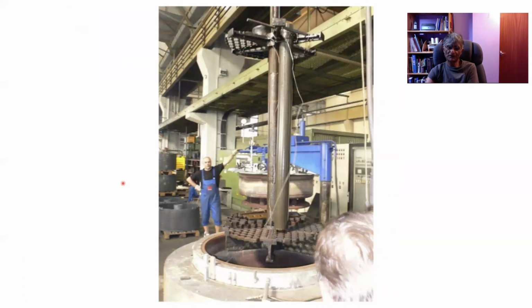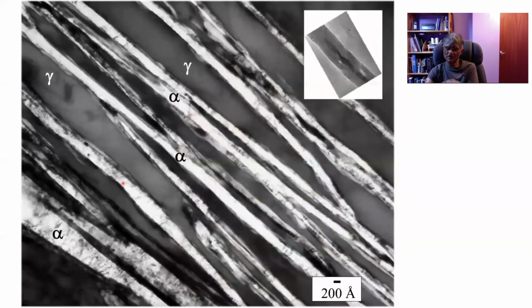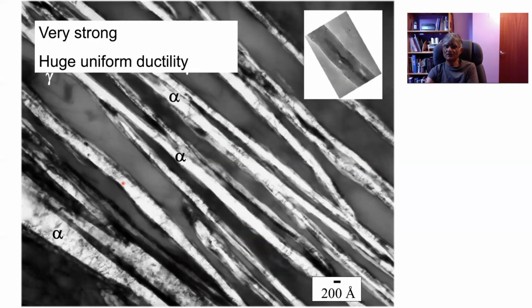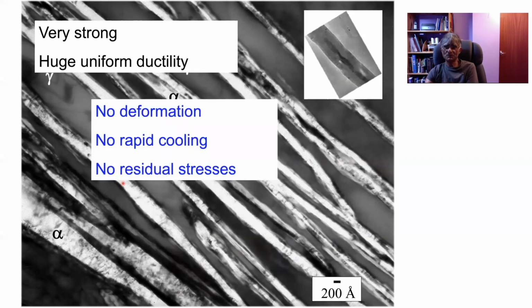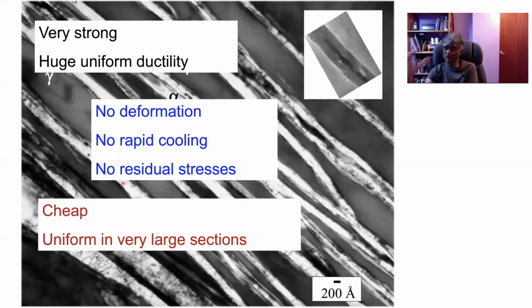Okay, so here are two of these shafts heat treated, and they have this structure throughout, uniform hardness through the section. So this is very strong. It has a significant uniform ductility. I showed you some tensile properties. We do not require deformation to produce this structure. There's no rapid cooling necessary, so you avoid problems of distortion, and no residual stresses built in from the cooling process. And you saw the chemical composition is not particularly expensive, and we can get uniform properties.